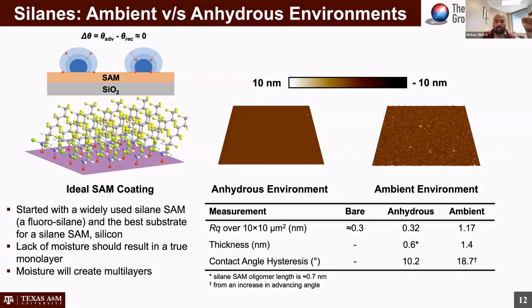If you look at the thickness of the controlled environment, the anhydrous environment, you'll see that the thickness is about the length of a silane oligomer. And if you look at the contact angle hysteresis again, you'll see that you have this extremely low contact angle hysteresis on the anhydrous coated surface.